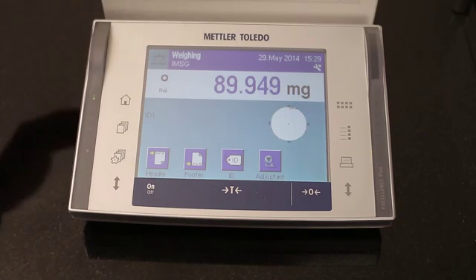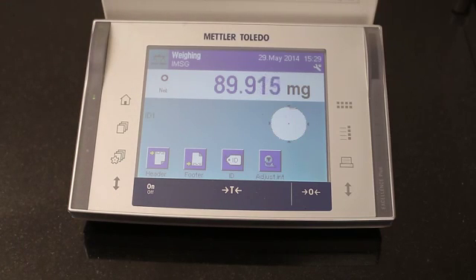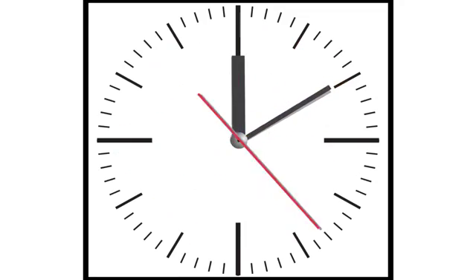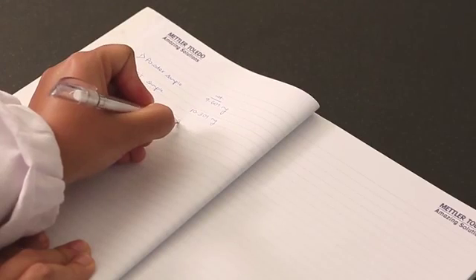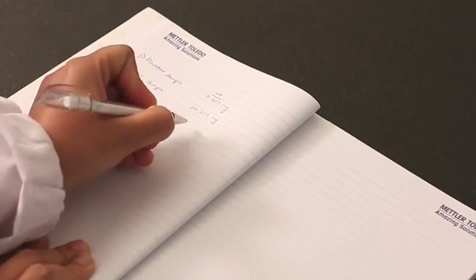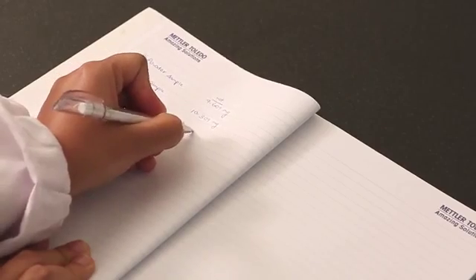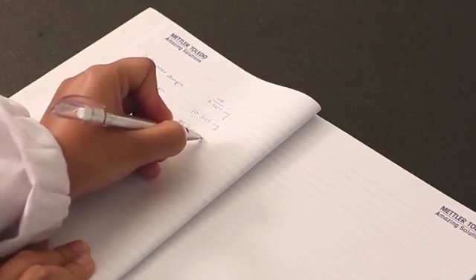Leave it on the balance for some time. The crucible is tight if the weight does not decrease by more than 20 micrograms within 5 minutes. Write down the weight in the laboratory journal. Such a correctly crimped crucible should withstand a temperature of up to 120 degrees Celsius when heated at 10 Kelvin